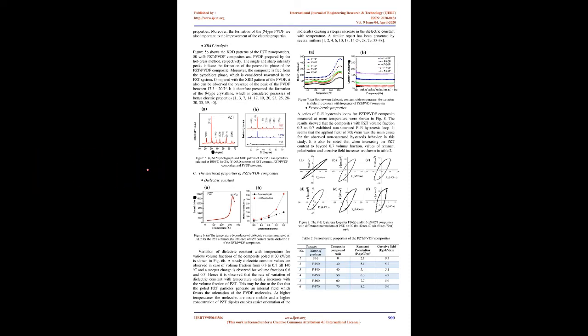However, for the hot press method with higher PZT content, the PZT grains are wrapped by the PVDF, indicating the connection characteristic of wrap and curl. The particles of PZT are much closer and the density of the composite is also higher, which favor the polarization of the PZT/PVDF composites and will enhance the electric properties. Moreover, the formation of the beta-type PVDF is also important to the improvement of the electric properties.